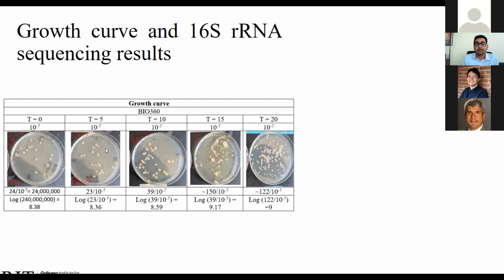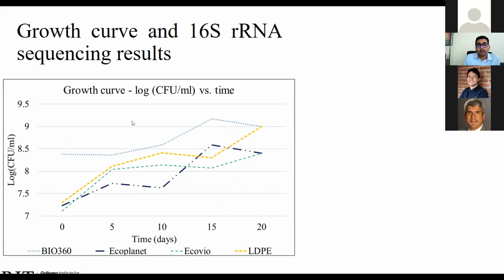And then at 5 days, 10 days, 15 days, and 20 days, you took readings. And as you can see, the number of cells, or the colonies, go up. And again, the cell count goes up. We were able to quantify that in a simple graph, which is the log of colony forming units per ml versus time. And you can see there's a half to 1 log increase in the growth of cultures. This kind of gave us an idea that the cultures are consuming these plastics. So we have isolated organisms which break down the plastics.